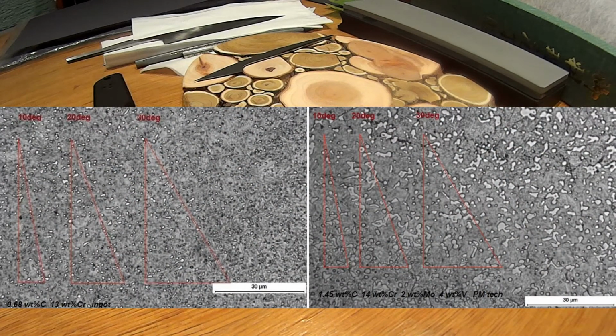On the left you have steel which is sold by the name AEB-L or Sandvik 13C26. On the right you have S30V, which is a very similar steel to Elmax. Vanadis 4, the knife I talked about, is somewhere in between those. It's actually closer when it comes to carbide volume to the left micrograph, because it has about 6% or maybe up to 10% of carbides, whereas AEB-L has 3% or even less of total carbide volume. And with red lines I illustrated the apexes of the knife edges at different angles: 10, 20 and 30 degrees. The little islands you can see on the micrographs are the carbides.